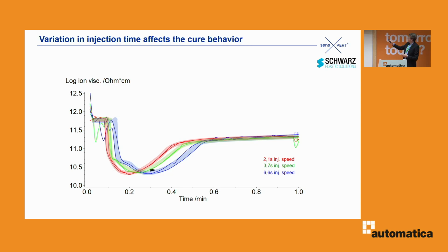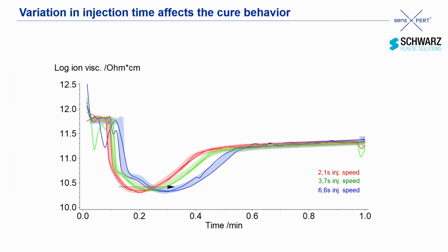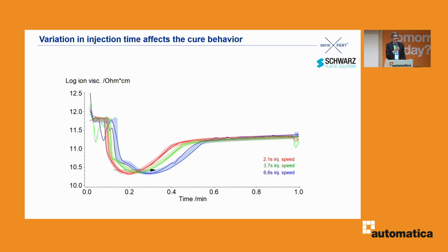And what we can see is, again, where the line is rising, so in the center basically, that's where the plastic cures, that's where it becomes solid. And what we can see is that this process is much faster if the shear is higher. So in this case, we have three different injection speeds, 2 seconds, around 4 seconds, and 6.5 seconds. And if we have faster injection speeds, we're pressing the material into the mold faster. The shear is higher, right? The flow conditions are more extreme, and this leads to the reaction kicking in earlier and going faster. And so this just is meant to illustrate how deviations in your production, in your machine settings, are going to change the way the material behaves in production.